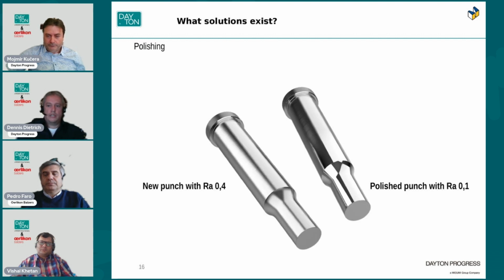This photo shows us a standard APX punch with a roughness of Ra 0.4. And on the right in the picture, a mirror polished punch with a roughness of Ra 0.1, which also can be produced at our production in Portugal. Polished surfaces reduce friction in the shear zone, which reduces the cutting factor and the cutting forces.